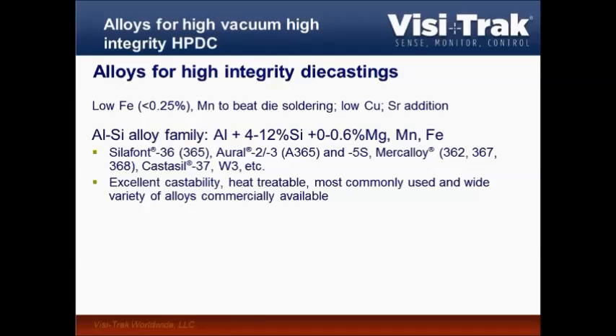We distinguish between, well, at least two major structural die casting alloy families. One is the typical aluminum silicon alloy family, with aluminum plus usually 8 to 12% silicon and up to 0.6% magnesium, then some manganese and a little bit of iron. It was found that up to about 0.22 or even 0.25, the iron is not harmful at the high freezing rate of die casting. If you look at typical structural alloys used for, let's say, aerospace castings, you will find iron level limits of 0.06 or sometimes even lower. Very common, because aerospace castings are typically made with precision sand, which means very low freezing rate. So it takes very long to solidify, and the iron has a long time to form these nasty needles.